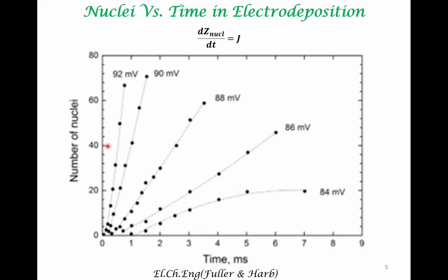But one nice thing about electrochemical systems is that you have a good control, in the sense that the knob which you can change is the overpotential. Supposing you are at an overpotential wherein there is significant nucleation, you can suddenly decrease the overpotential so that nuclei are no longer formed.